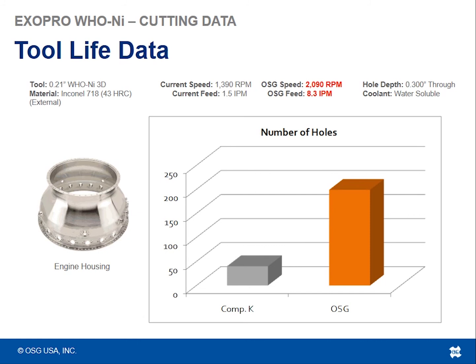This is a 300 thousandths deep through hole with a water-soluble through tool coolant, and we were able to almost quadruple the number of holes that this customer was able to get. So very satisfied customer there.